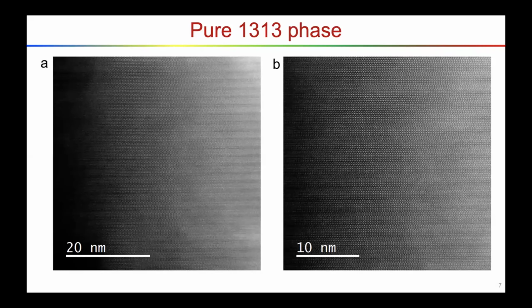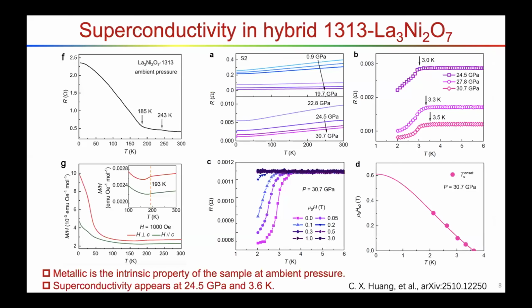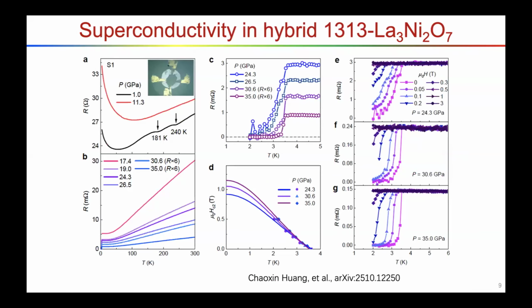Maybe last question, Hua Zhou, please. It's a very quick question. Very interesting about this SDW transition, because all the temperatures you estimate for the SDW are based on transport measurements, right? The kink on the RT curve. After applying pressure, when that kink disappears, is that exactly the same time you see superconductivity, or is there still some overlap or crossover?